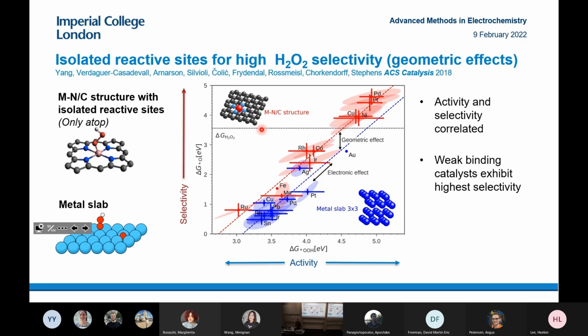So usually the way I think about it is a model surface is something you can aspire to on a real three-dimensional surface. But in some cases, it's difficult to synthesize some moieties on a two-dimensional surface. That tells you what you could expect if you optimized everything really well. What we usually found as well when we did try these platinum mercury alloys in a real device, we found the selectivity was much worse than in the rotating disk electrode experiment, because we think the mass transport of the hydrogen peroxide is much worse when we've got much higher current densities. We end up going for much more inert catalysts like carbon, and having to tolerate high overpotential to get maximum current density, maximum selectivity.